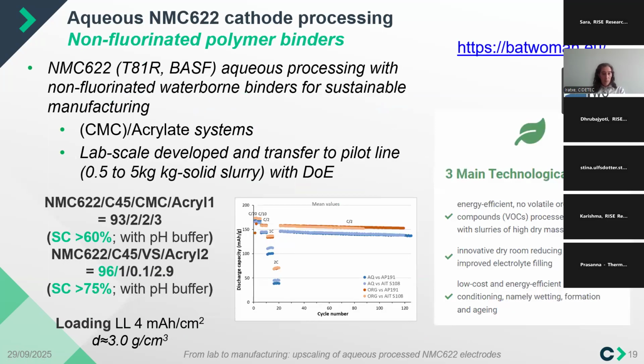I want to also provide some further developments with fluorine-free polymer, which is again a latex, a stable suspension in water, but based on acrylates, another family of polymers, non-fluorinated, in which we have gone further to increase the cathode active material percentage. This NMC622 is not particularly developed for water-based slurries, so it's the use of phosphoric acid, adjusting the amount for the particular NMC, and also adjusting the whole final pH of the final composition and the particular polymer binder being used.